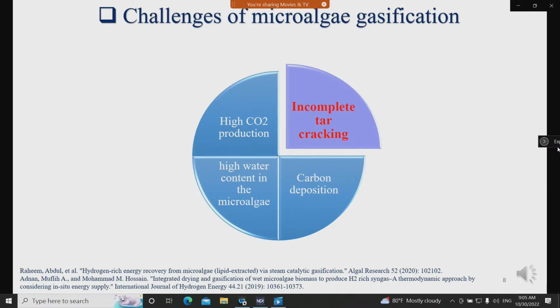But the most crucial problems found for microalgae gasification include these four problems. Formation of tar during gasification has been reported as the main challenge during microalgae gasification. Handling of high water content in the microalgae is another important challenge. The water content of the cultivated microalgae usually varies between 75 and 98% on the wet basis. High carbon dioxide proportion and carbon deposition during microalgae gasification are considered as two other challenges.